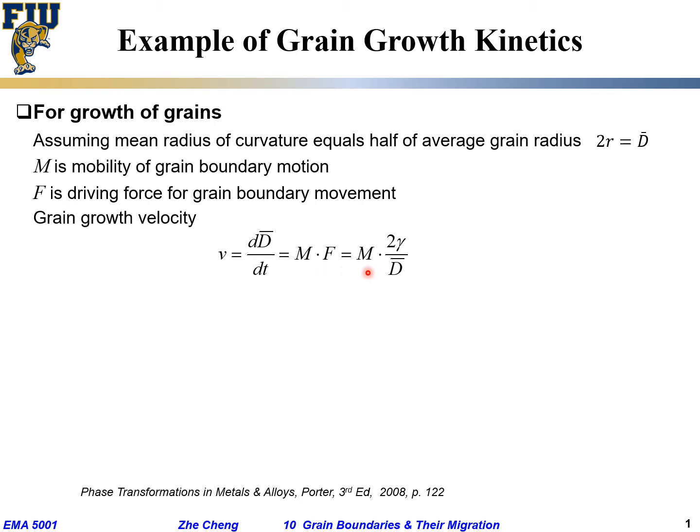From what we learned before about mobility, what is the driving force? From previously, using the curvature, it would be 2γ (interfacial energy) divided by your radius of curvature. So I was wrong, I should have r instead of D̄ here.